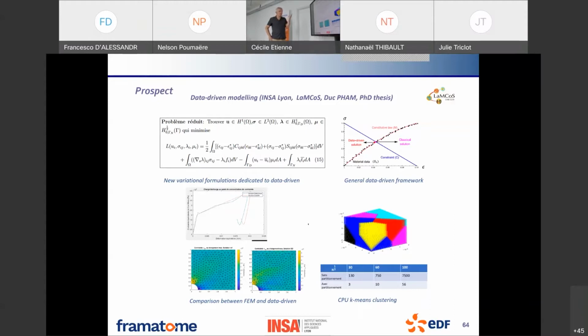Here, for instance, you can imagine to have digital image correlation in order to have experimental data on a surface, or microtomography in order to have experimental data, displacement field and strain field in the bulk of a component. However, it is not so easy to have the dual quantity, I mean the stress field, in terms of experimental data. So we have also to account for the ability of the specific physics, I mean, for instance, nonlinear solid mechanics, to be able to have such data. Okay, so particularly the stress field.